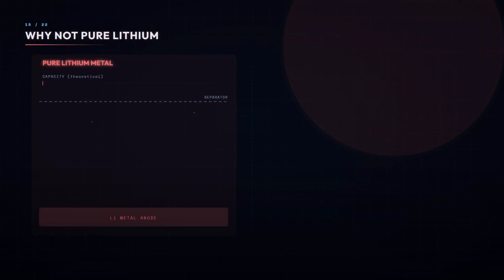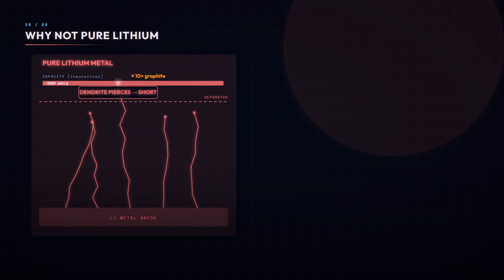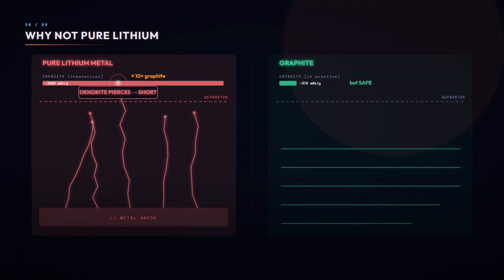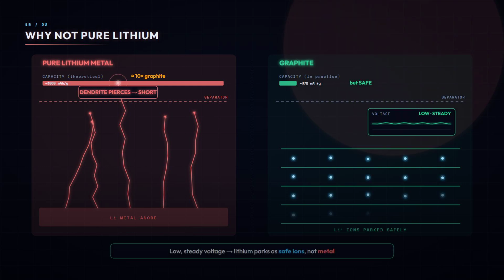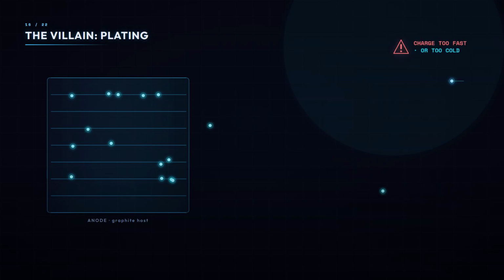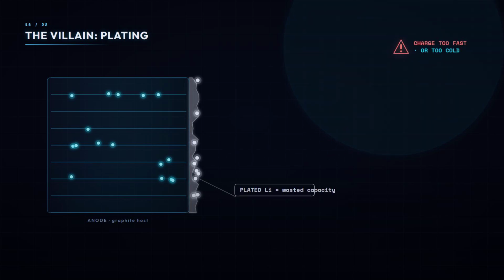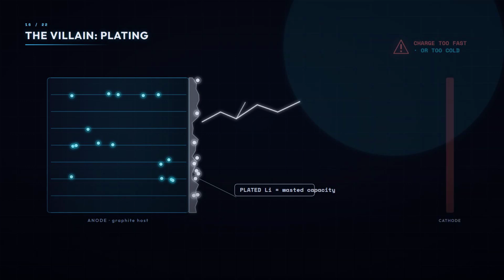So why not skip graphite and use pure lithium metal, which holds vastly more charge? Because metal lithium grows dendrites, tiny needles that pierce across the cell. Graphite wins by working at a low, steady voltage, so lithium parks as safe ions, not metal. That danger still lurks. Charge too fast or in the cold, and you push the anode so hard that lithium stops slotting in and instead plates onto the surface as metal. That plated metal is wasted capacity, and it can grow the very dendrites we feared.